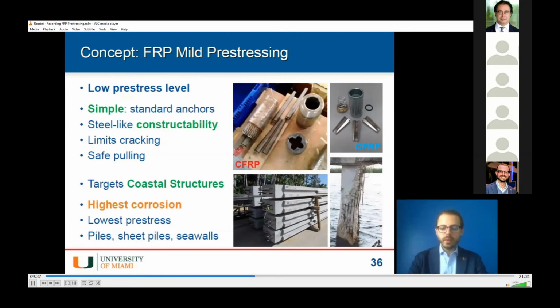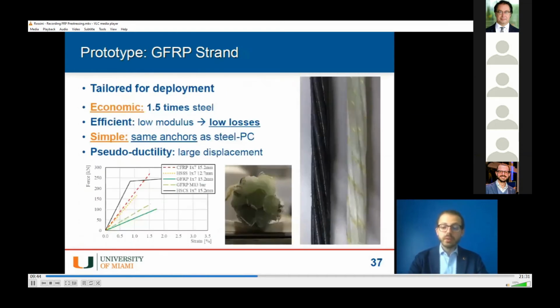If the solution that we want to adopt is reducing the level of pre-stress in our structure, we need a material that makes it reasonable from both the cost perspective and the mechanical efficiency perspective. We believe that this material is glass, particularly in the form of a 7-wire strand, of which you see a prototype in these pictures. Glass is more economic than carbon. It comes at 1.5 times the cost of steel, and is going down as more manufacturers are coming into the game. It's a more efficient technology for pre-stressing because it has a lower modulus that results in lower pre-stress losses. If we reduce the level of pre-stress, as already said, we can use simpler anchors. And also glass is a pseudo-ductile material in the sense that it can achieve larger displacement with respect to carbon at a lower level of stress.